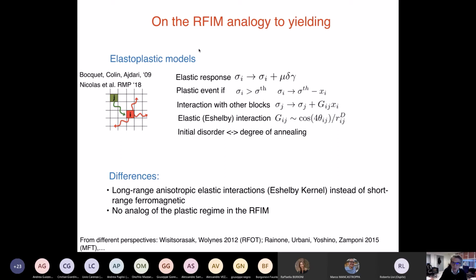It is redistributed using the kernel called G_ij, which is what is called the Eshelby interaction, and it tells you, if locally I deform, how much this local deformation or local change of stress is transmitted far away. You can work this out using elasticity theory. For example, in 2 dimensions it has this quadrupolar form, which is cosine of 4 theta ij, where theta ij is the angle you can define in 2 dimensions between i and j, divided by r_ij to the d.